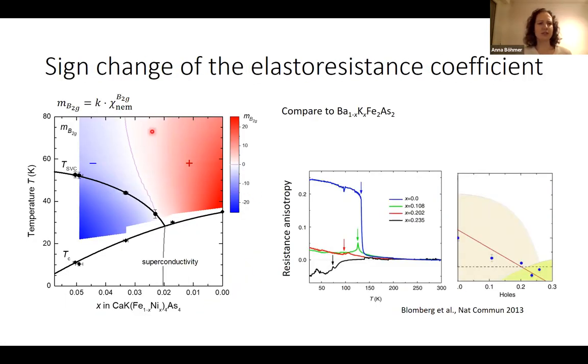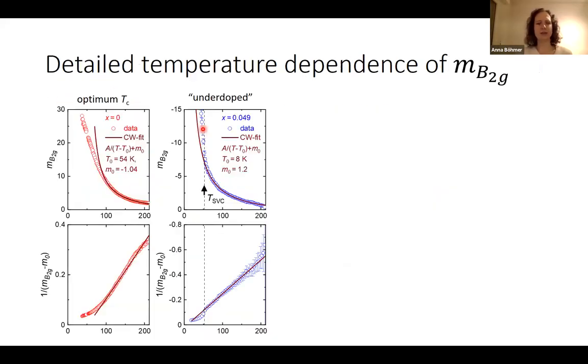So what we also see is that in vicinity to the sign change, the temperature dependence becomes rich. So there's a sign change as a function of temperature as well. And that must also be related to this prefactor. But we think that maybe if we go far enough away from that sign change, we can learn something about the temperature dependence of the nematic susceptibility from the temperature dependence of the elastoresistance on these extreme compositions. And that's what I've shown here.